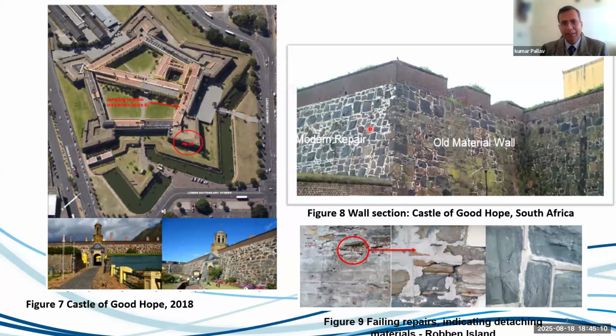And what even happened in this case is that soon after this repair was done with the cement, because of porosity, these walls breathe through the lime mortar. During the rainy season, they absorb moisture, and during the dry season, the moisture goes out of it. But this doesn't happen once you do it with your cement. So what has happened is that the repair which has been done pops out, because these walls are very thick, and because of this permeability, they try to throw the material out of it, right? So that is a major problem in this type of treatment which you do for restoration purposes. And it also doesn't look aesthetically nice for a structure of national importance. So we can go for the next one.